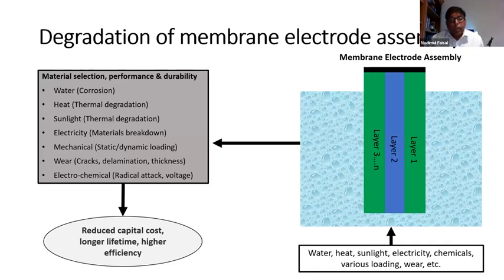So eventually, once you have manufactured, then you have to look into the degradation. If it degrades very quickly, then that is unwanted. It will be a huge economic loss, because those are important materials you can't keep replacing all the time. So it needs to be water resistant, with less corrosion, and the thermal degradation should be less under heat or sunlight. Because of voltage, the material should not break down. If the electrolyzer is used in static or dynamic loading conditions, you need to look into the mechanical integrity, and then tribological behavior like crack, delamination, wear, and so on. And then electrochemical attack, like radical attack, voltage. So all these factors have to be looked into when you're designing an electrolyzer.